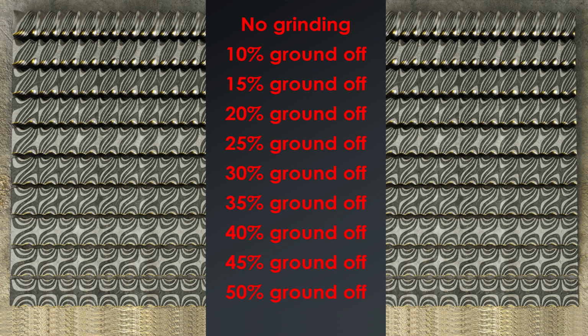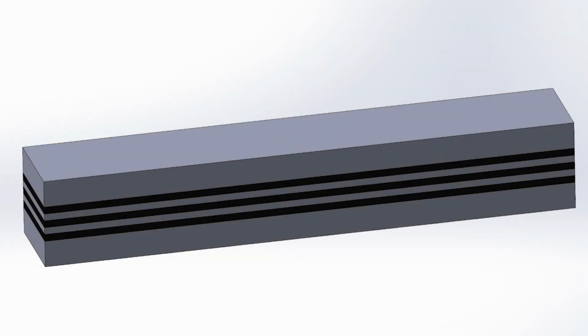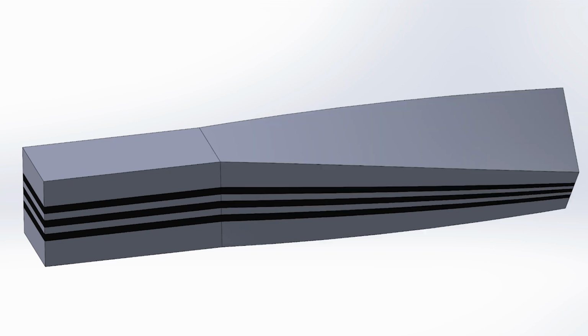This is a real twisted billet with grinds from about 5% to 50%, made by a fellow bladesmith, Niels Provos. It illustrates what we have been describing earlier. This is a short clip showing you the process of twisting a billet a couple times and then grinding progressively from one end to the other and then back.